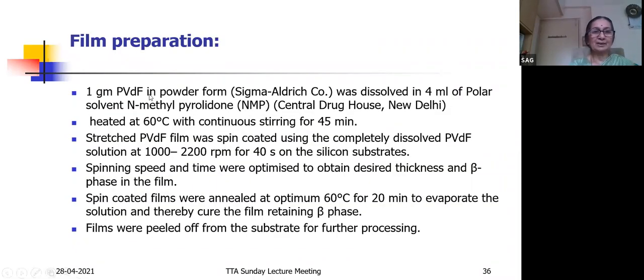We took a PVDF powder of 1 gram. It was dissolved in a solvent, N-methyl pyrrolidone, NMP, and it was heated at 60 degrees centigrade with continuous stirring for 45 minutes. We stretched the PVDF film by spin coating using a completely dissolved solution at a rate of 1000 to 2200 RPM for 40 seconds. These are optimized parameters.